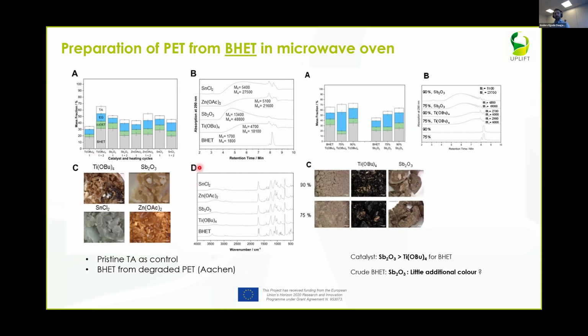But what is maybe more interesting is if we go in here on the SEC data and we compare the titanium data, which you can see here, and the antimony data, which you can see right above. And compared to what we saw from the terephthalic acid hydrolysates, we actually see here that the antimony catalyst is better for the BHET. So there is a preference for the different catalysts, where one is more suitable for transesterification, whereas the other one is more suitable for direct polyesterification from these systems.